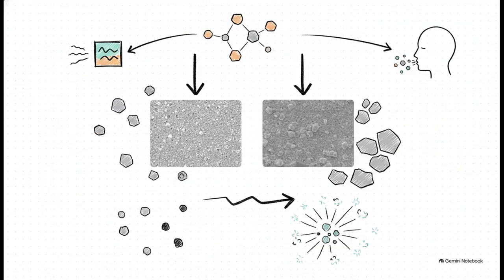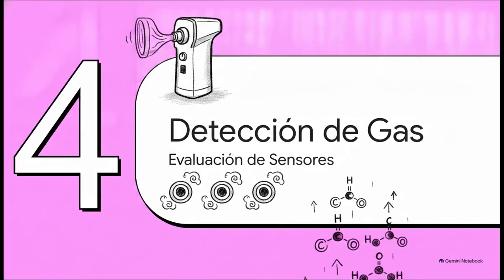Looking at the topography under the scanning electron microscope really drives this point home. If you compare the 90-minute pure film with its gadolinium-doped counterpart, you can see both maintain nice, uniform surface coverage. But the gadolinium clearly acts like the brakes. It inhibits individual crystalline growth. It totally modifies the particle size and leads to this distinct surface agglomeration. And that's exactly what we're looking for. This finely tuned, bumpy morphology essentially means we have a significantly higher number of active sites ready to interact with the surrounding gas. Let's move on to Section 4, Gas Sensing Results, the moment of truth.